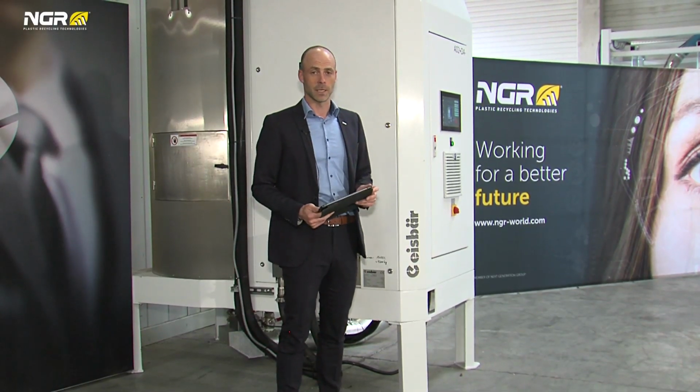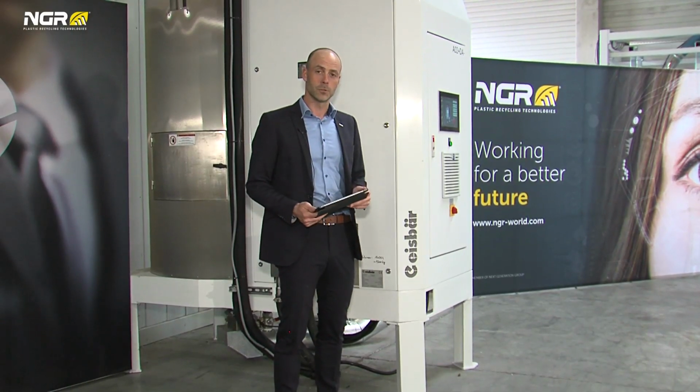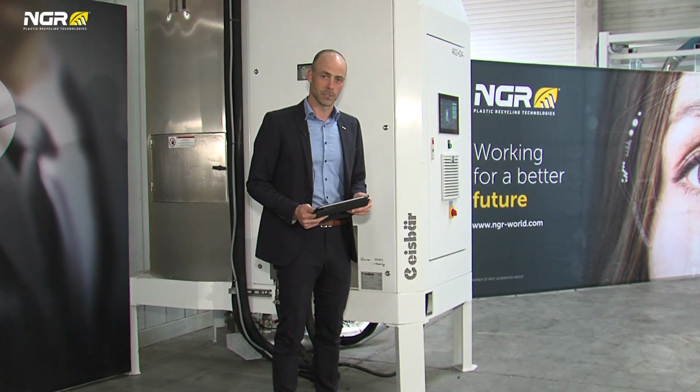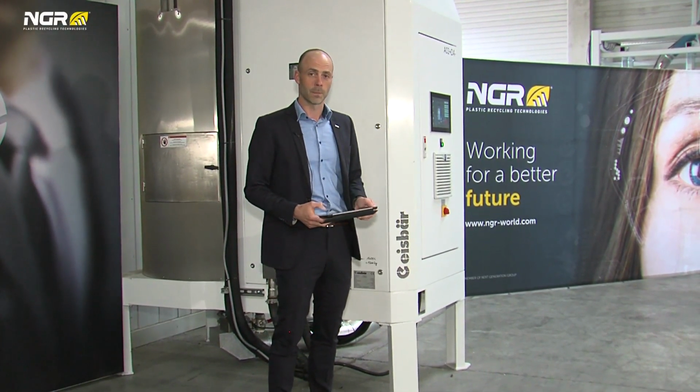After the crystallization process, the pellets take a rest in the dealdehydization system to achieve the customer requested AA level. Due to the fact that the pellets enter the dealdehydization system already at 150 degrees, the additional energy investment is very low. After the dealdehydization and before filling, the pellets will be chilled in a cooling hopper. The hot air which comes out of the cooling hopper will be used for the crystallization process at the very beginning. This leads to a closed loop and energy efficient process.